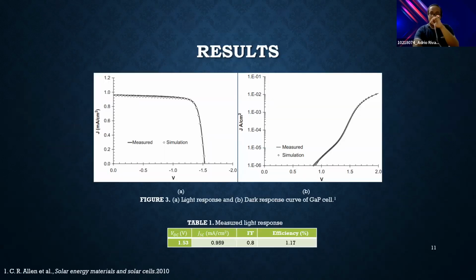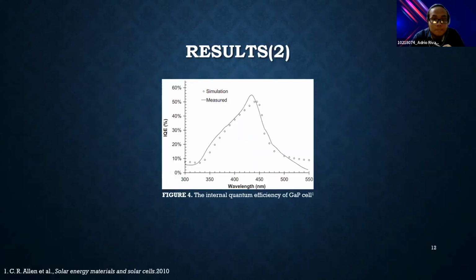And this is the result of the characterization of the cell. Figure 3A is the light response of the gallium phosphide cell, and Figure 3B is the dark response of the gallium phosphide cell. From the measured light response, we also get the open circuit voltage and short circuit current, respectively 1.53 volts and 0.959 milliamperes per centimeter squared, with a fill factor of 0.8 and an efficiency of the cell of 1.17%.